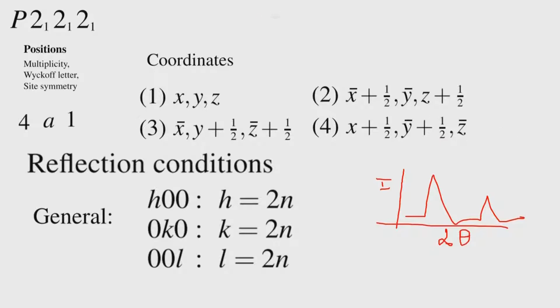After determining the intensities, we now examine the systematic absences. When we examine the systematic absences, we find that we can determine the space group. Some of them get determined uniquely. So, we determine the space group, and that is the issue. Space group determination therefore involves both the geometry and the intensities in its own way. Even though we still do not have the structure information, we have the intensity distribution available to us. The way intensity is distributed is decided by the nature of centering of the lattice, or for that matter the presence of symmetry elements in a given direction.